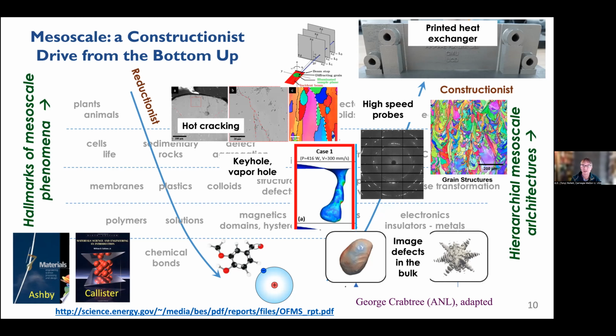to dislocations, where we know perfectly well what the properties of dislocations are. We can calculate them to a very large extent. But when we try to connect dislocations as individual defects to, for example, work hardening behavior, you deform something, it gets harder. How do we calculate that from first principles? Pretty tough problem, not really a solved problem as yet. So it's an example of mesoscale science, in my head at least.